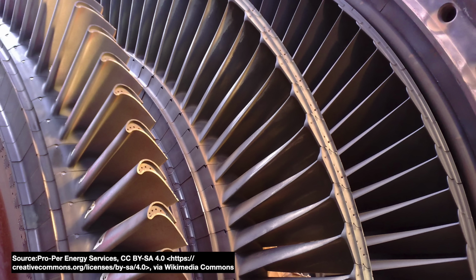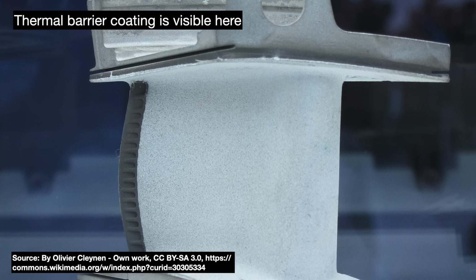Engineers have incorporated cooling measures to maintain the metal's internal temperatures at about 80 to 90% of their melting points. One thing they do are thermal barrier coatings to reduce how much heat eventually reaches the superalloy surface. This barrier coating usually ranges about 100 to 400 micrometers thick. These coatings can be just as complicated as the metals they protect. They have to remain on surfaces for tens of thousands of hours while enduring the metals underneath them repeatedly stretching and shrinking with rising and falling temperatures.